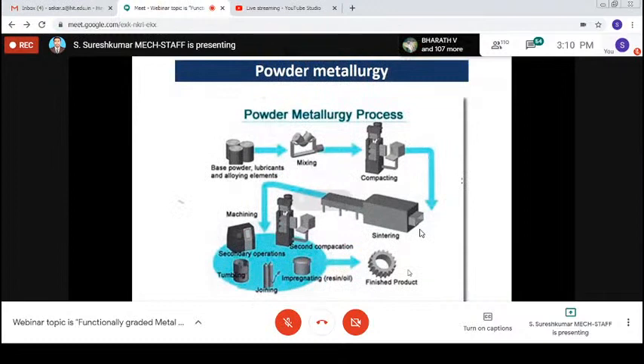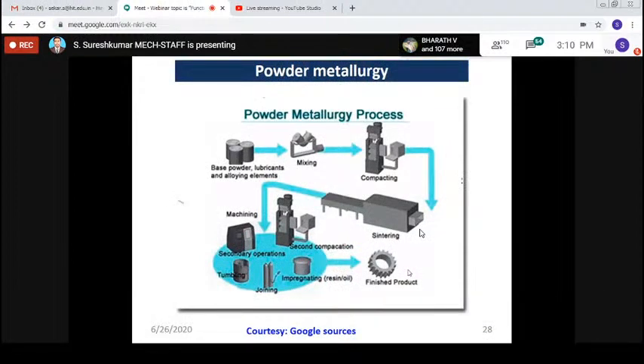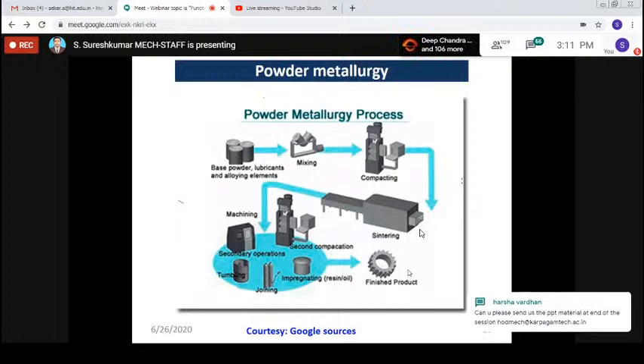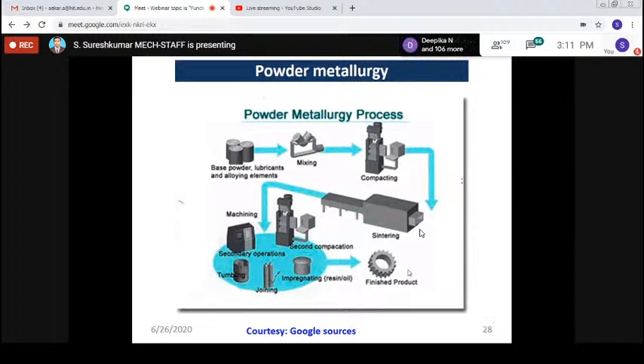Okay. Powder metallurgy is a solid type of composite material fabrication technique. Here you can use the material in powder form, so you can mix the material. For example, I will go with aluminum powder, and the reinforcing particle you can blend and mix, and you can pour it into the die, where the material is subjected to compacting under higher pressure. After compacting, you can keep the sample in the furnace for the sintering process, the heating process. Sintering may be done at almost 80-90% of the melting point of the matrix. So now you can produce the composite material.